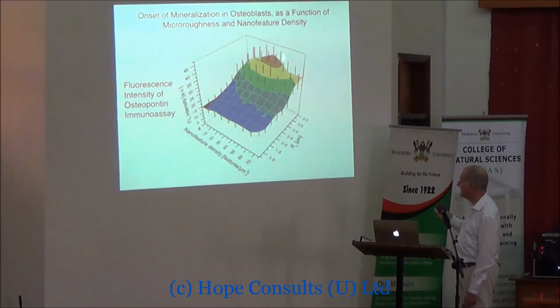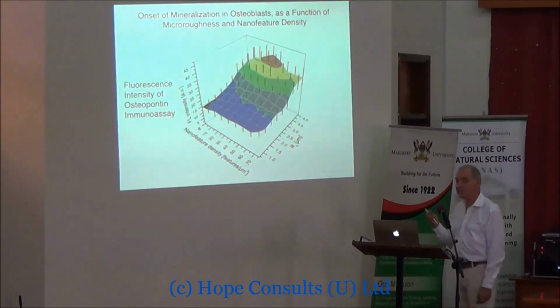But what's interesting is at this end of the microscale gradient, if we look at the nanoscale gradient, we also have an optimum in nanoscale roughness on top of the microscale roughness, which seems to be interacting and causing more osteopontin production. So there seems to be some kind of synergistic behavior between the two scales of roughness.